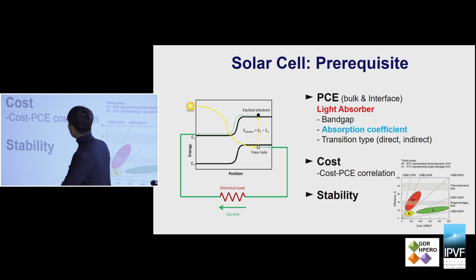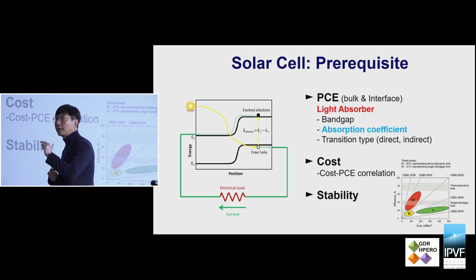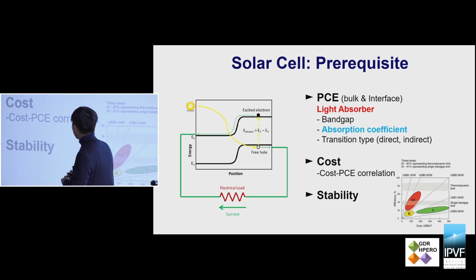And when you select a light absorber, there are three important parameters you have to consider: band gap energy to utilize panchromatic light absorption, absorption coefficient, and the transition type, direct or indirect. Mostly a direct transition is better than an indirect transition. Among them, the absorption coefficient is most important, because if you have a high absorption coefficient, then you can decrease the penetration depth.